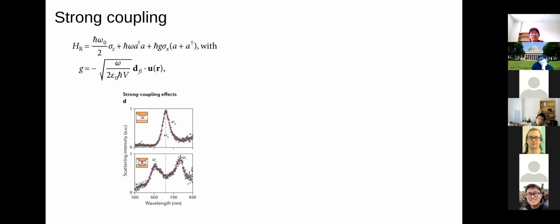So there are experiments that have been done that essentially put an atom in an extremely tiny cavity, and the cavity is small enough that the effective coupling parameter becomes sufficiently large that you can observe this kind of Rabi splitting by then sending in an additional weak probe and mapping out the resonances.